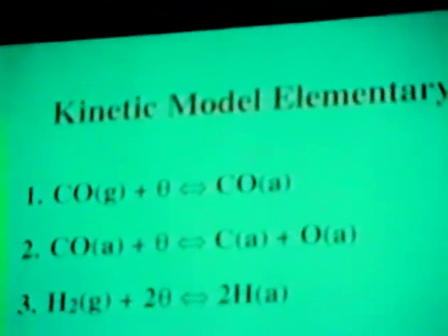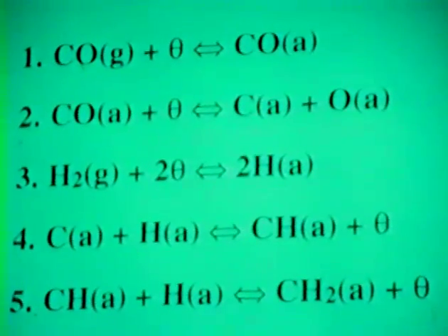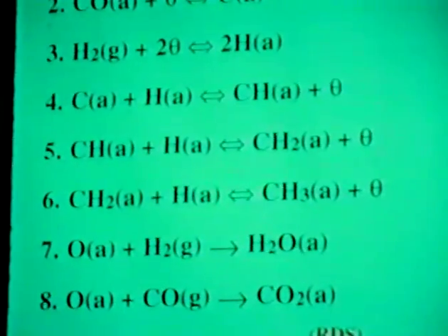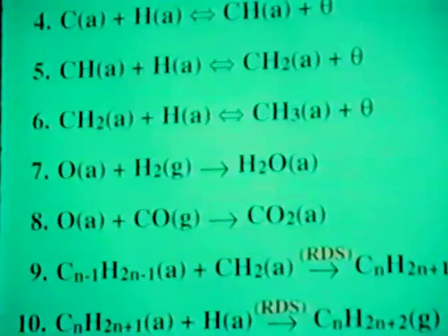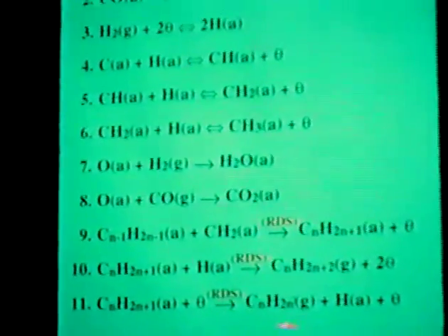Well, we've seen that each of those parameters can vary quite significantly, and a power law expression does not really allow for variation in those reaction orders. So we're now going to look at a model based on elementary steps and see if we can develop a model which is consistent with the data, which does allow for some variation. The steps are CO adsorption and dissociation, hydrogen dissociation, and stepwise addition of an adsorbed hydrogen to an adsorbed carbon species to form the CH, CH2, or CH3 species.